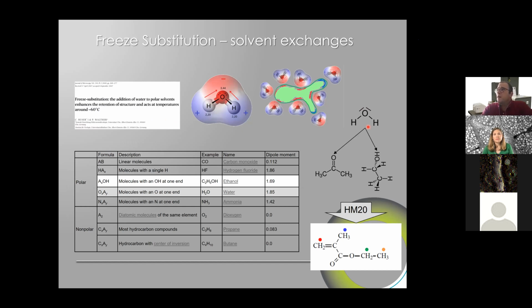What is interesting is that the polarity of the solvent will influence the type of freeze substitution and the contrast we will gain. There was a very beautiful paper about that that came out in 2007, which showed that preserving some water in the freeze sub cocktail will preserve the contrast. One way to understand that is that full dehydration of your proteins might collapse the fluorescence and might dehydrate the proteins so much that the stain has a hard time getting into the proteins to contrast them.